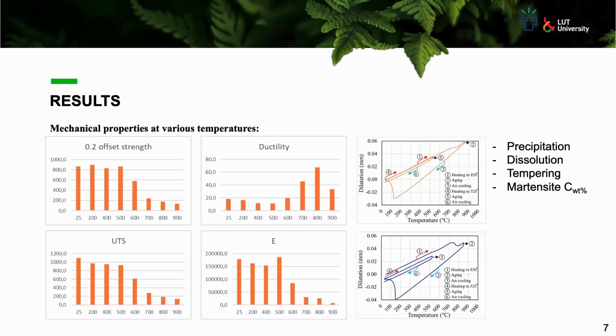And after all of these, let's get into the focus of this presentation, the mechanical performance of this material under high temperature. So as you can see, in the as-built version, up to 500 degrees, no significant change is apparent in the strength of the material. However, after 500, there is a sudden decrease down to 800.